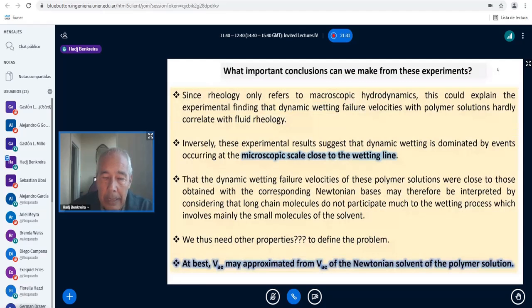And if you see in here, these are all the data put together, and in here also all the data put together. So we see that a small addition of polymer affects the rheology of the solution significantly, but the critical velocity for dynamic wetting failure is very little affected. And the work, as you see in here, is in the AIChE Journal, 1998. So what we are saying is that what is important is the rheology at the microscopic scale.